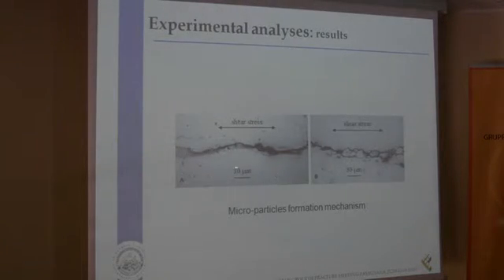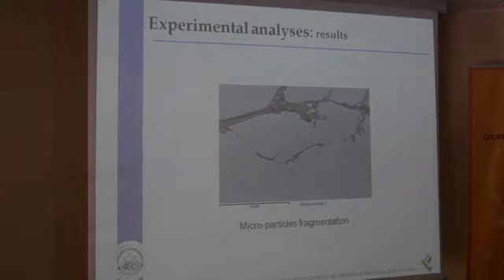This is a picture showing in more detail the phenomenon of microparticle origin. We can note an incipient detachment of these particles from the crack faces, interfering during cycling contact, and also the typical wavy aspect of the crack. On the right, we can note the same phenomenon in a more advanced state, where the microparticles are almost completely detached from the surface of the crack. In some regions, these microparticles were also further fragmented, appearing like a sort of gray band between the crack faces.